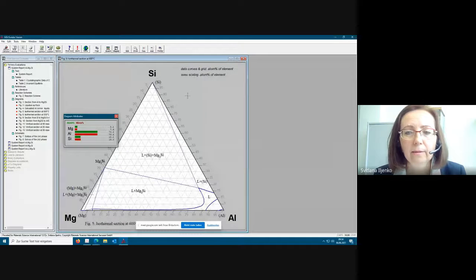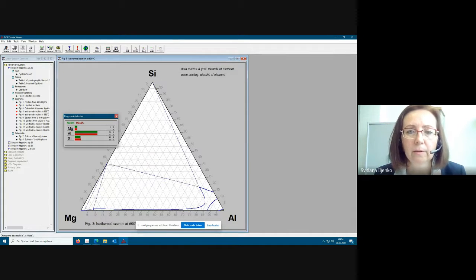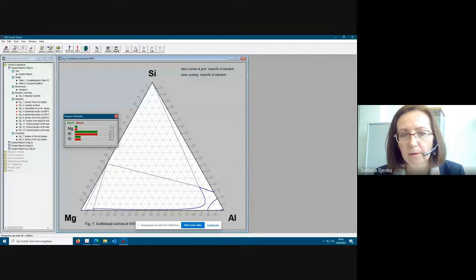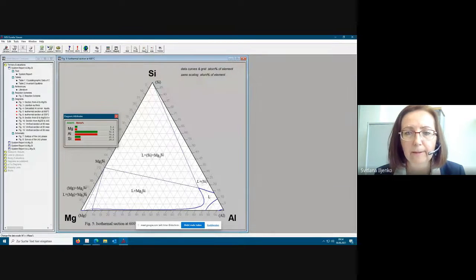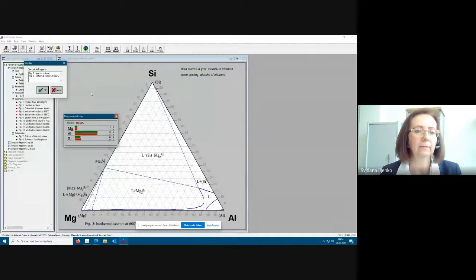Except for that, I can convert the entire diagram. As most of the diagrams are presented by default in atomic percent, I can convert them easily to mass percent by just clicking these two buttons, and then my entire diagram is in mass percent already. I go back. Another interesting feature is an overlay of diagrams. If we want to compare, for example, the character of phase equilibria, how it's changing with changing temperature, then we take, now in this case I have 600 degrees as a thermal section.